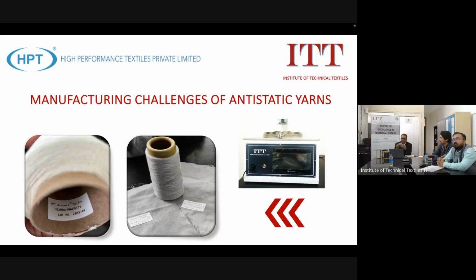When we are using this type of fiber, we need to blend it with other materials, and we pass it through blow room, carding, draw frame, speed frame, and ring frame to make yarn. On the other side, sometimes clients need a grid form in the fabric. Just to give you, I don't know if this is visible, this type of fabric, if you see it closely, you'll see a black grid every 10 centimeters in both warp and weft direction.